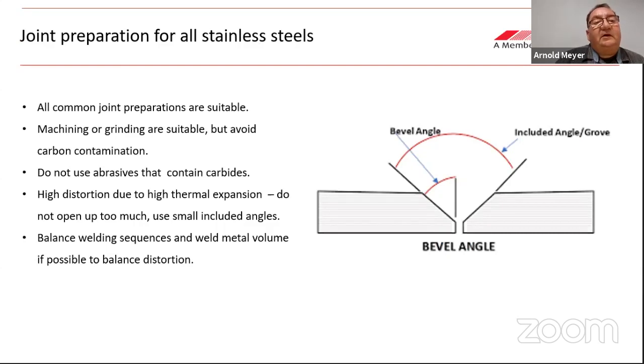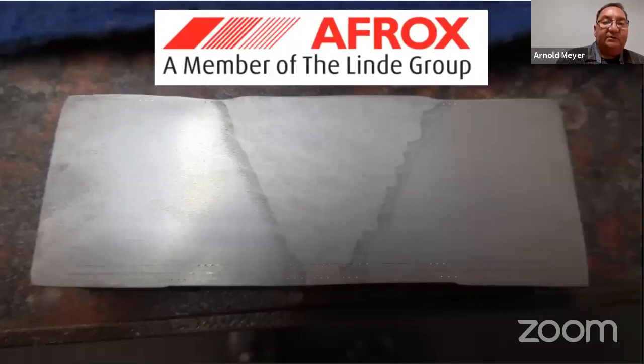If you quickly look at the joint preparation, all common joint preparations are suitable. Machining or grinding, but don't use carbon-containing abrasives. Remember that stainless steels have high thermal expansion. If you weld materials with high thermal expansion, you want to limit the volume of the weld metal, and you also want to limit the amount of heat that you put in. So keep them as narrow as possible, but widen them up enough to get fusion. And then balance the welding sequences and the weld metal volume on both sides of a plate or on both sides of a pipe in order to balance the distortion.